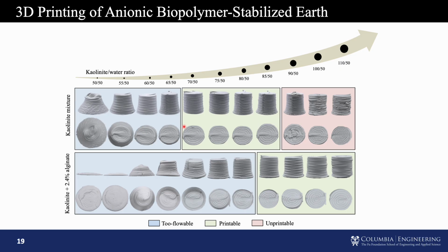However, when we add 2% sodium alginate, what is going to happen, as we already saw in the previous slides, is that it will reduce the storage modulus and reduce the yield stress, which is very obvious from the first few figures here. So it will immediately destroy its buildability. But what is really interesting here is that it will push this printability window to a higher solid volume fraction. Basically, sodium alginate helps to smoothly and continuously extrude the material at a higher solid volume fraction, which eventually results in high compressive strength and also low drying shrinkage because you have less water in these printable mixtures.